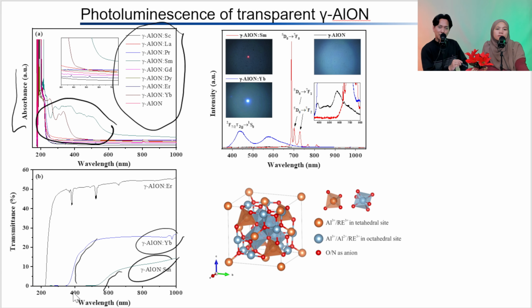So, because of that it can generate specific peaks. This is the photoluminescence spectra here, and you can see that when doped with ytterbium it shows a different color, like a bluish white color, and with samarium it shows a red color. So when doped with certain rare earth elements, it may change the properties of the absorbance and the photoluminescence property. Wow. You have lots of experiments, and most of them have different colors, right?